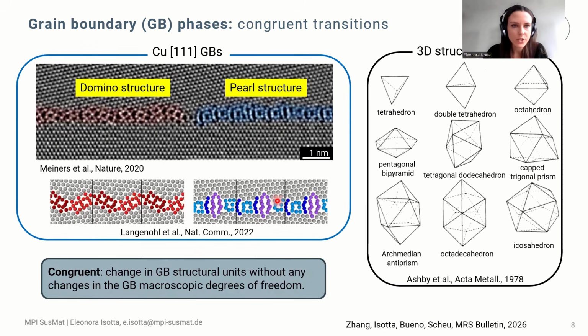We can see one of such examples for copper grain boundaries here, where it was observed a coexistence of two types of structural units, a domino structure and a pearl structure, happening at the same boundary. You can see here a little bit of a simulation of the same boundaries. The coexistence is also a proof of the presence of a transition, and in this particular work it was reported that according to the tensional state of the boundary, one would happen to prevail over the other.